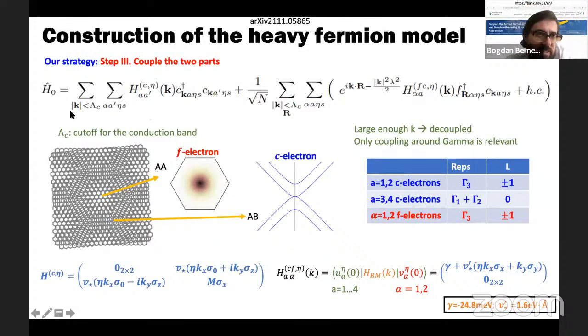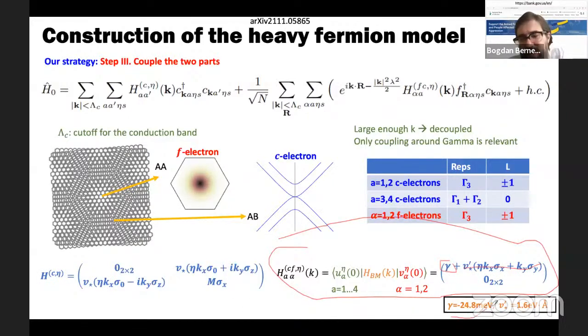And the coupling of the two parts can also be understood by symmetry. It has some form that is given here. Okay? And you can basically understand it just by a constant. Forget about this term, it's small. This constant is actually quite large, it's around 24.8 millielectron volts. So this constant is the coupling between the gamma 3 representation of the f-electron and the double vortex. And this is large. And this will give rise to the band gap of the Bistritzer-MacDonald model.